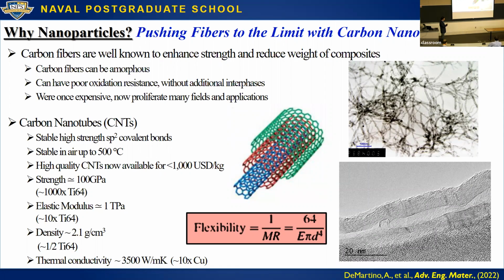You can see the individual layers here. You have maybe about 15 to 20 layers in this tube. The individual layers have the same properties as the nanotubes. We like using these nanotubes in composites for two main reasons. One is that, unlike with polymers, where you can do a lot of processing at even room temperature or slightly elevated temperature, for metals you're going at minimum to a few hundred degrees Celsius. And for ceramics, for the most part, you're going above 1,000 Celsius for processing them. So we're trying to process these materials with nanotubes at those very high temperatures.